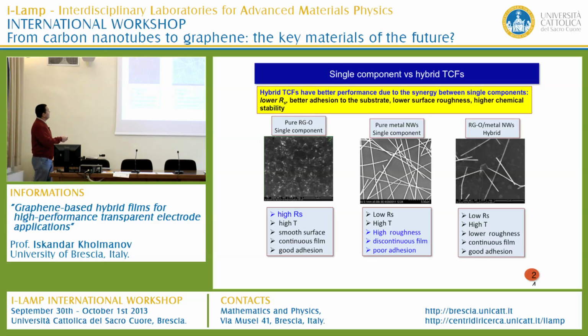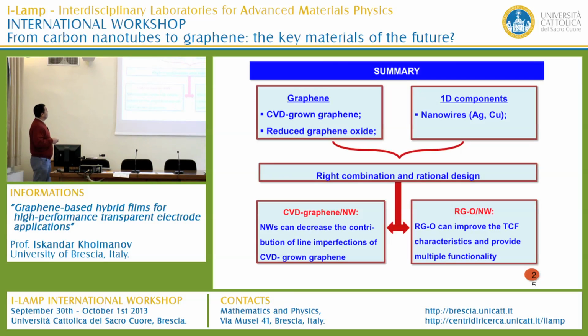So, summarizing our hybrid film, this is a pure RGO single component film. The main disadvantage of the RGO film is a very high sheet resistance. And pure metal nanowires have very low sheet resistance and very good optical transmittance, but the disadvantages are high surface roughness, discontinuous film, and poor adhesion. So when we assemble these two single component films, we obtain hybrid films where these disadvantages can be minimized or completely eliminated. This is a summary of my presentation.